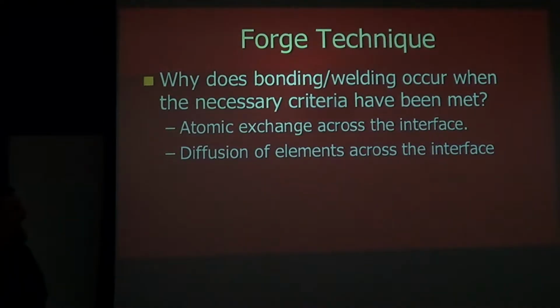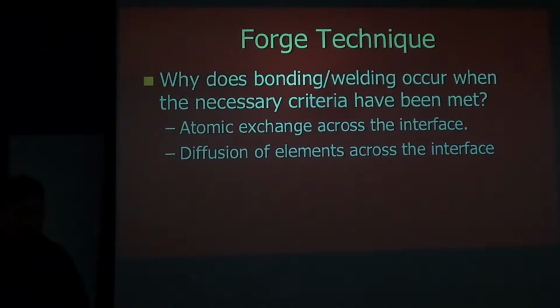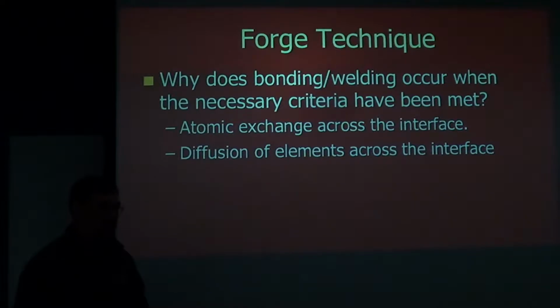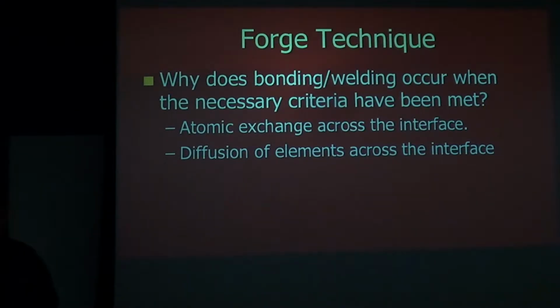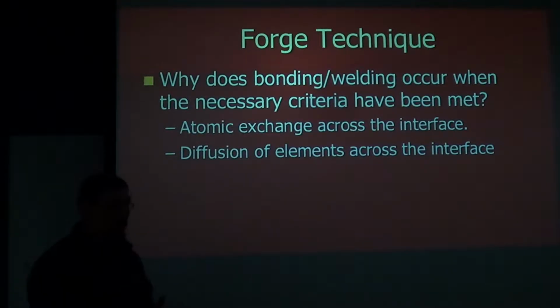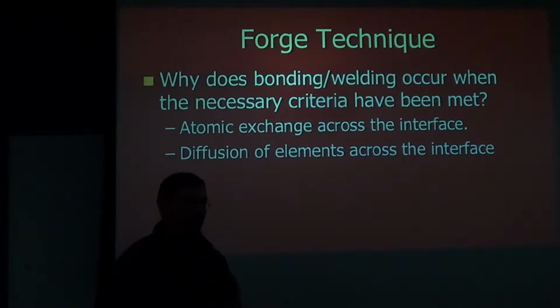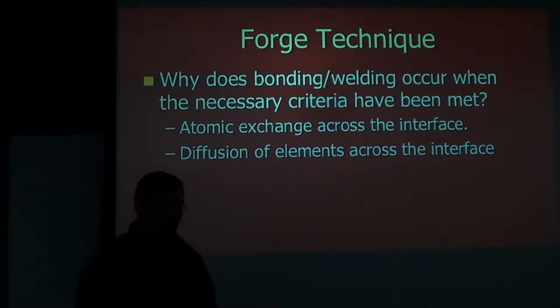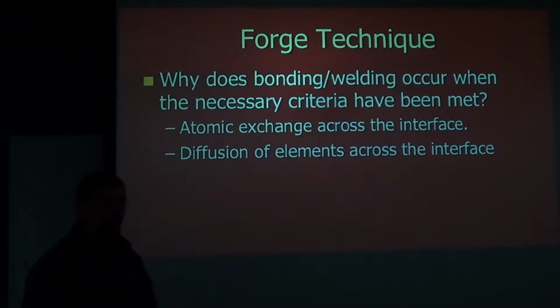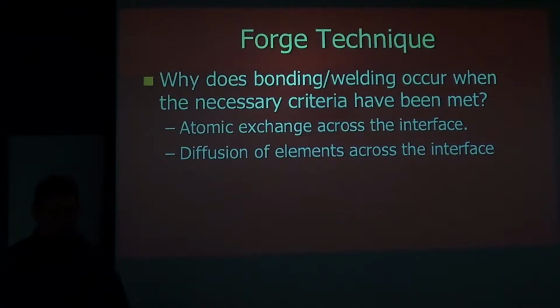So why do we get bonding when this happens? And the answer shows up there automatically. It's because we have atoms that are moving across the interface that we've created. Initially, you just have a few atoms that move across that interface, but over time, you'll have actual diffusion taking place. So you heard Dr. Metzloff mention that in certain pattern welded materials where you have different carbon contents, you can end up with a fairly uniform carbon content over time due to the diffusion of carbon between high and low regions of carbon. It wants to even itself out. So you will get diffusion across interfaces, and that will enhance the bonding.